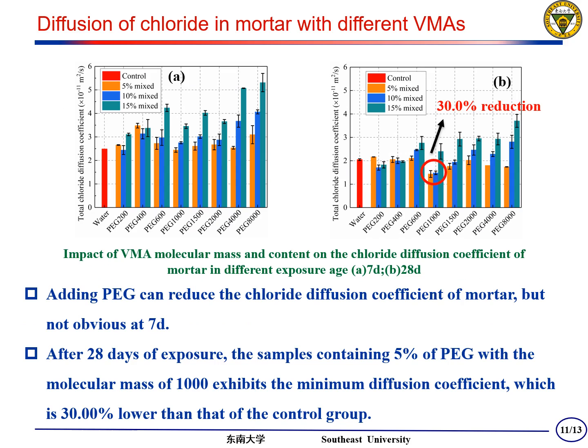Adding PEG can reduce the chloride diffusion coefficient of mortar, but not obviously at 7 days. After 28 days of exposure, the samples containing 5% of PEG with a molecular mass of 1000 exhibit the minimum diffusion coefficient, which is 30% lower than that of the control group.